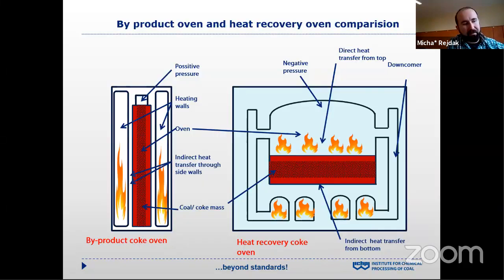Apart from the aforementioned differences in the geometry of the chambers, the main difference is the method of heat transfer to the coal charge. In byproduct ovens, heat is transferred to the coking blend indirectly through the ceramic walls between the heating flues, where coke oven gas is combusted. The waste gas has no contact with the coal charge. Due to the relatively low width of the charge, the coking process time is usually between 16 and 23 hours, and the escaping coke oven gas is discharged from the chamber directly to the collecting main.